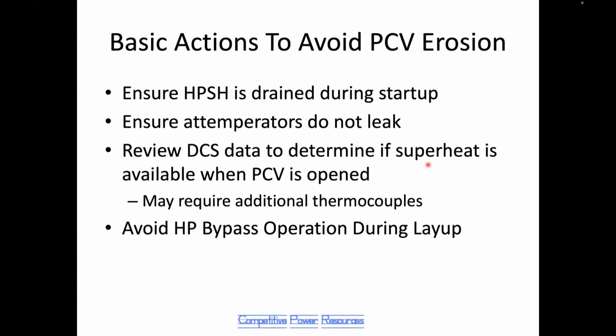Discussions with the designers of these valves, it looks as though something on the order of 25 degrees C superheat is sufficient to protect the valve from damage. You may have to install additional thermocouples on the pipe work upstream of the bypass valve in order to get sufficient steam temperature information to make this decision about when to open.